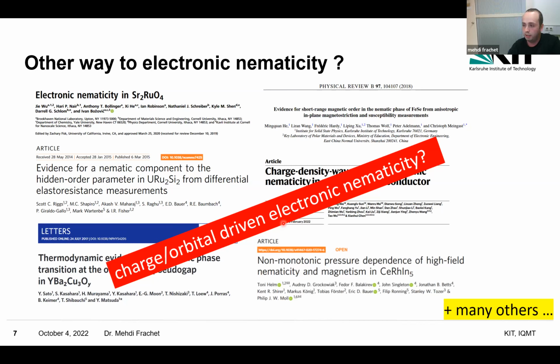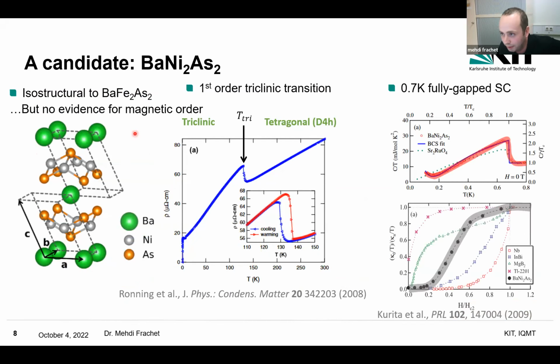And that's particularly interesting because, as you know, in many unconventional superconductors there are, for example, charge density wave instabilities. So that's where our BaNi2As2 is interesting. That's our candidate for this type of nematicity. A few things to mention: it's a compound which is isostructural to BaFe2As2. It has the same tetragonal structure at high temperature. But so far, there is no evidence for long-range magnetic order.